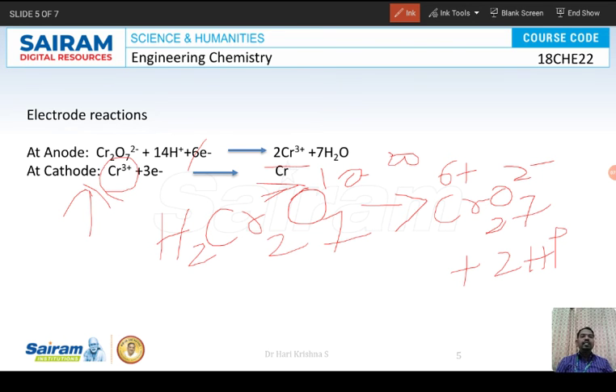The anodic efficiency is 100%, but the cathodic efficiency is 10 to 20%. Because of that, there will be an increase in the concentration of Cr plus 3 in the bath. Cr3 plus will deposit on the surface of the cathode, which gives black deposits. That is one reason. Another reason is that chromium has a high negative electrode potential. Because of these reasons, we are not going to electroplate chromium using chromium anodes with the anode consumption method. Instead, we are going to use the electrolyte consumption method.